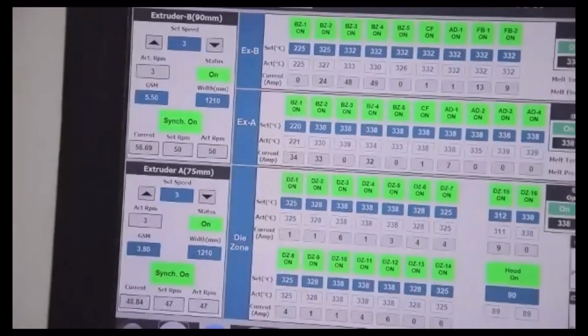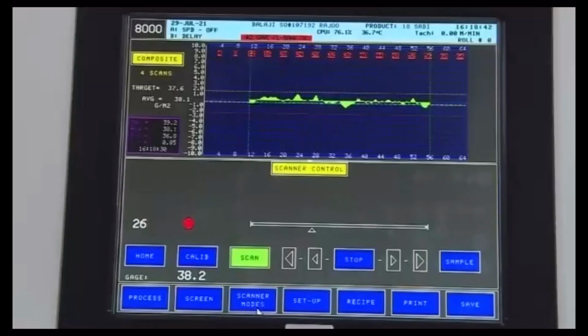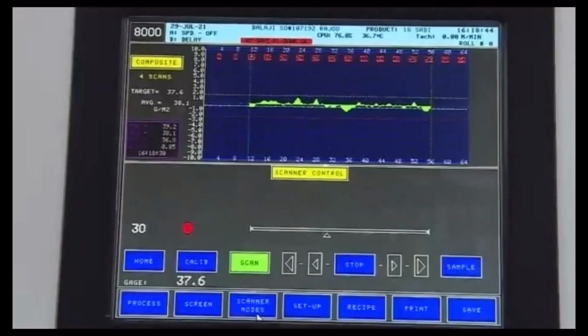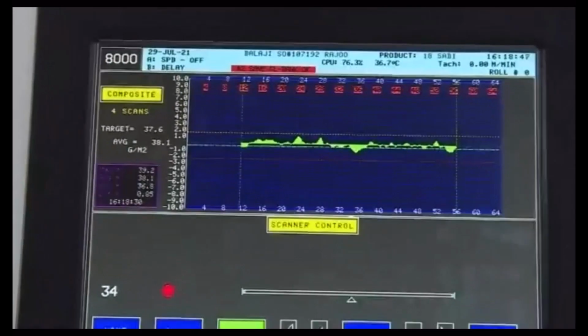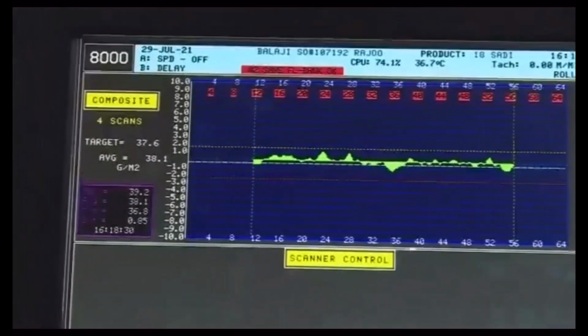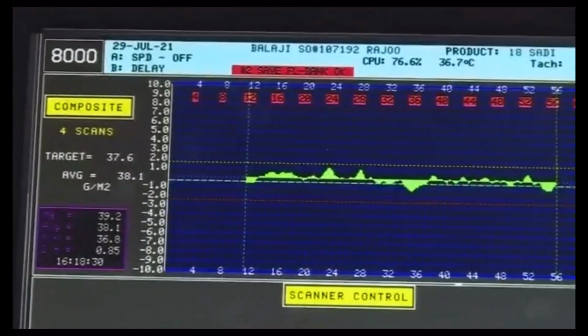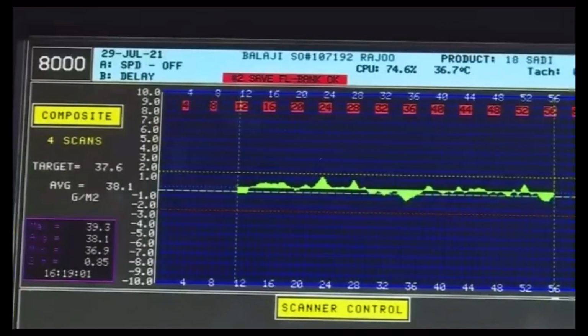We talked about the beta sensor measuring the total thickness of the laminate. This screen from NDC continuously shows the thickness profile. It's a lovely profile right now. As you can see, the target thickness is 37.6 GSM and the average is 38.1. And right below, you can see the thickness variation based on 2 sigma, it's 0.85. It's really commendable to have a GSM variation of 0.85 on a 37.6 or 38 GSM of laminate.